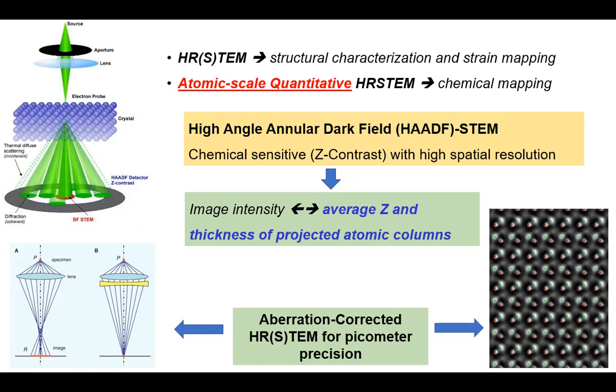Well, for that purpose, you need high-angle annular dark field STEM, which is chemically sensitive. So the image intensity depends on the average Z number, the atomic number, of the projected atomic columns. This is why it's called Z contrast, but it also depends on the thickness of the TEM sample. And today, with the new aberration correctors, we can visualize the atomic positions, the atomic columns, either with high-resolution TEM or high-resolution STEM with picometer precision.